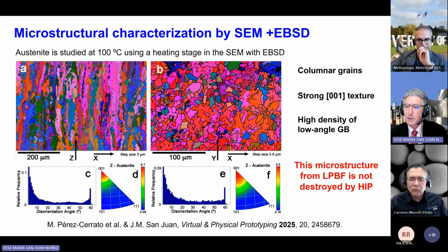An interesting point is that this microstructure from laser powder bed fusion is not destroyed by hot isostatic pressing. In fact, these images are taken just after the HIP on the laser powder bed fusion sample. So this means that the columnar microstructure and the texture is maintained after the hot isostatic pressing.